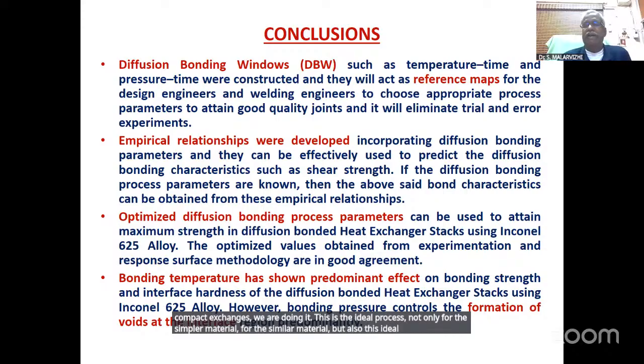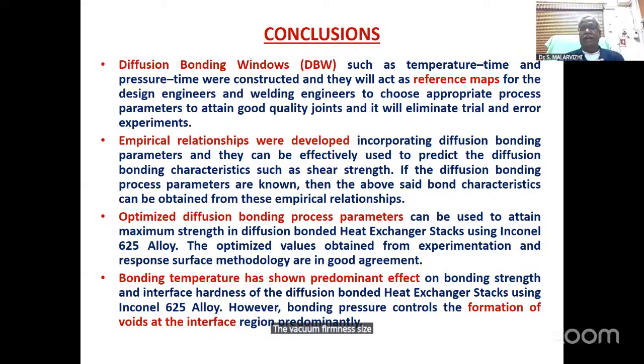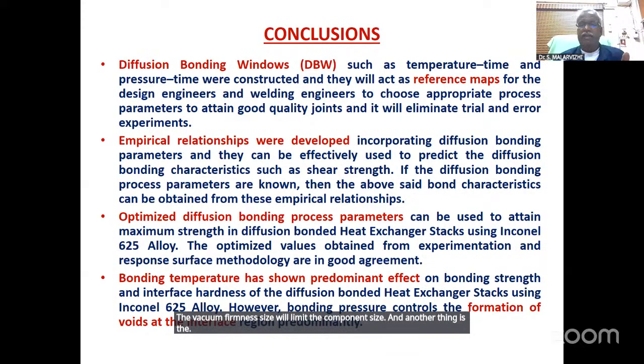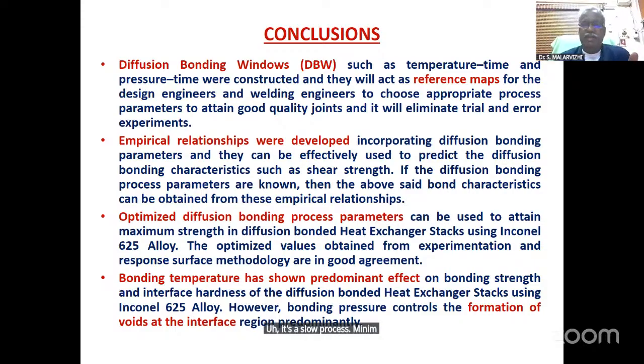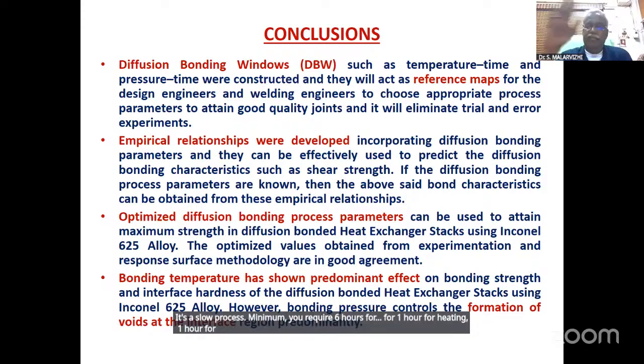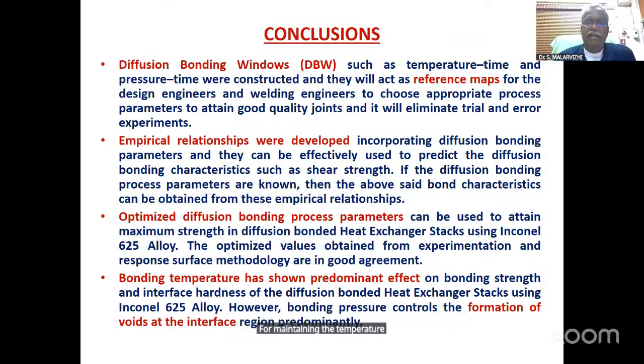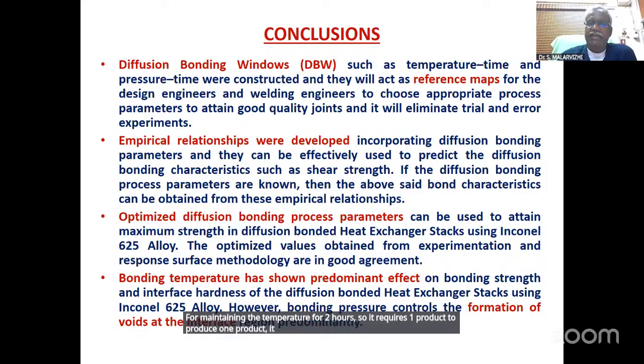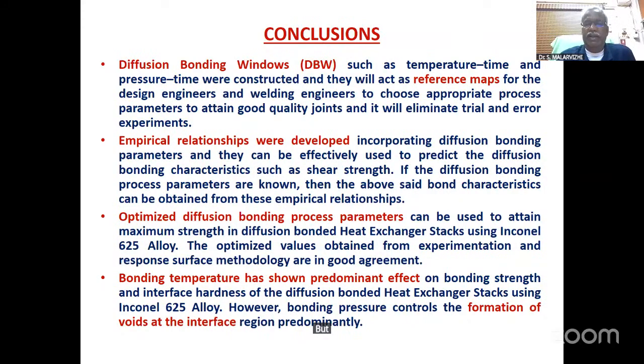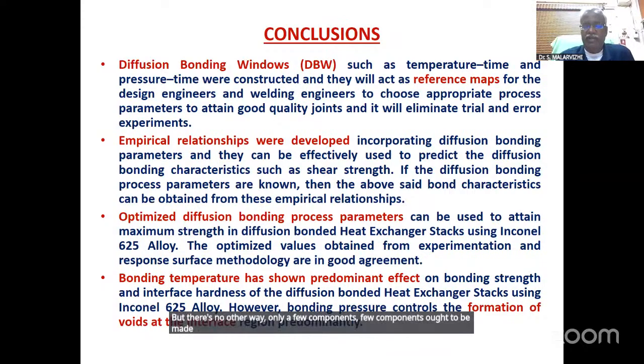The only problem is the vacuum furnace size will limit the component size. And another thing is it's a slow process. Minimum you require 6 hours: 1 hour for heating, 1 hour for cooling, and 2 hours for maintaining the temperature. To produce one product, it requires 6 hours. But there's no other way. Only a few components are to be made using this process.